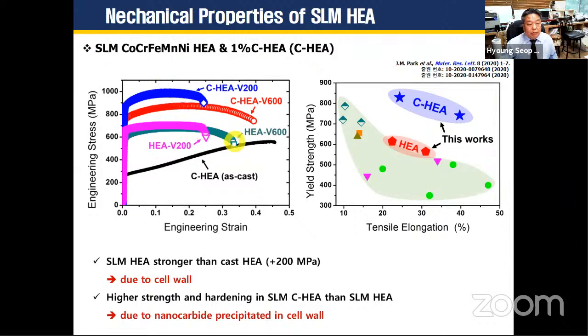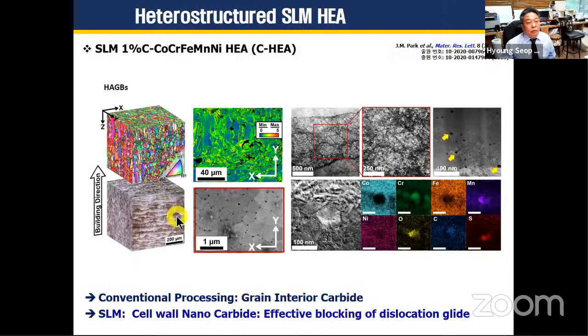This superior mechanical properties combination, a good combination of strength and ductility, this banana curve in the UTS plot, is due to the fine cell structures and nanocarbide in the cell walls for carbon containing high entropy alloys. And it's well known that for conventional materials, conventional process carbon-added high entropy alloys produce coarse grain interior carbide. There are many inside carbide and very coarse. That results in the reduced ductility.